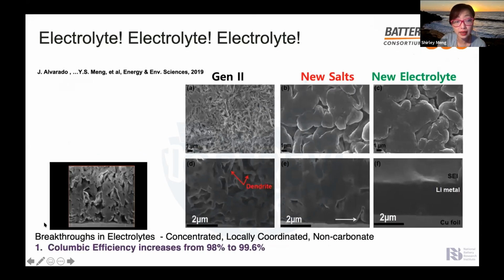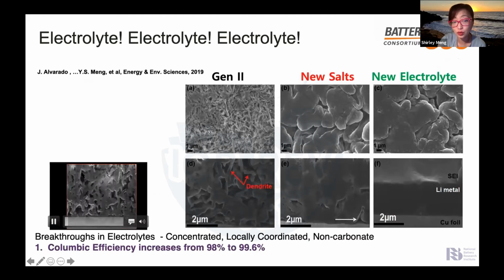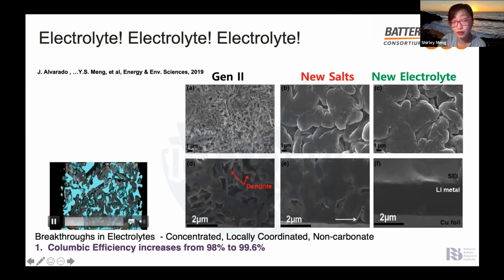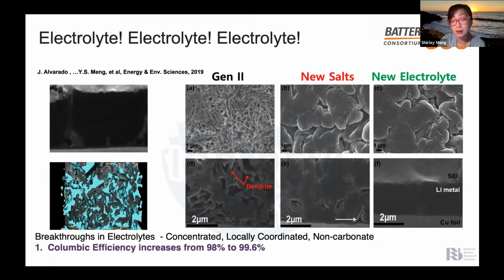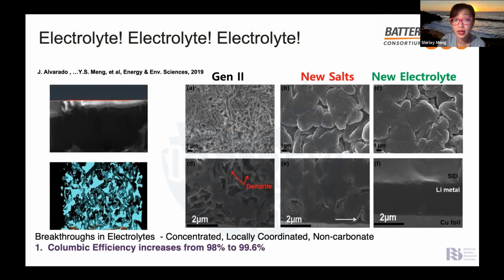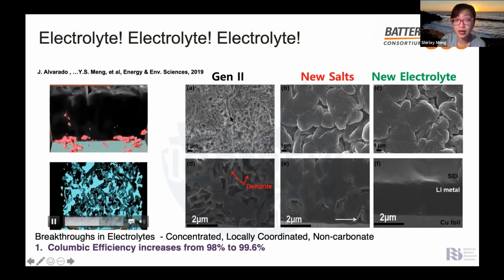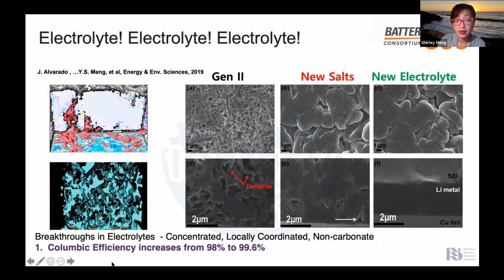So with this tool, we can now evaluate the different electrolyte. So you can see in the carbonate electrolyte. So this electrolyte is designed for graphite. If you use this electrolyte for lithium metal batteries, you grow this kind of highly porous lithium metal, okay? But if you change the electrolyte, you can then see the microstructure of the lithium is completely different. So when we change the electrolyte from carbonate electrolyte to ether-based electrolyte, the Coulombic efficiency increased, and many people attribute that to the improvement of the solid electrolyte interface.